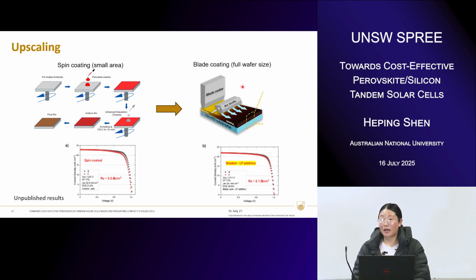That is the effort we are devoting at ANU, and we have been able to demonstrate some promising results through extensive engineering of the perovskite compositions as well as the deposition process. For example, using the blade coating method, we were able to get comparable cell performance with that of the spin coating. Now we are applying this technology on large area, over 100 square centimeter tandem cells, to demonstrate high efficiencies. Hopefully we will have more results I can share with you in the near future.